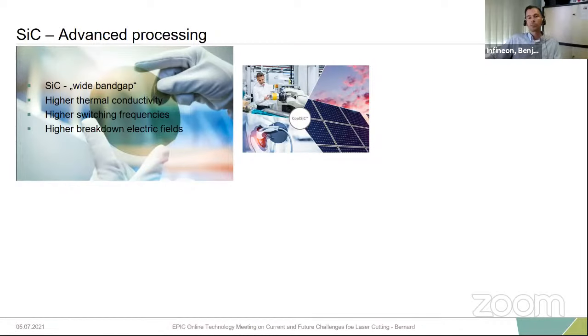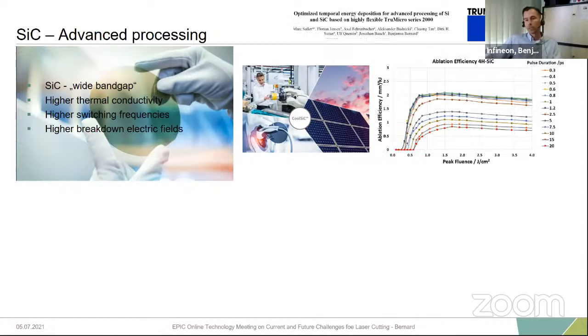And to gain some knowledge here, we teamed up with TRUMPF. They have a very nice setup where they can easily scale down the pulse duration on one laser head, which is very attractive. But what we find out is that silicon carbide behaves similar to metals. We see here that at 1 picosecond, we reach more or less the maximum efficiency, and reducing pulse duration is not leading to any beneficial ablation behavior anymore.